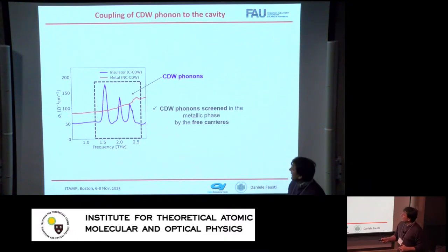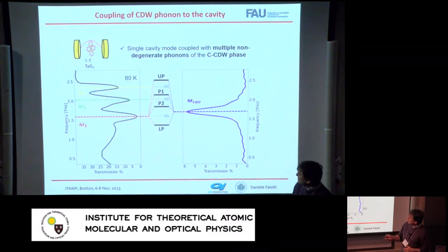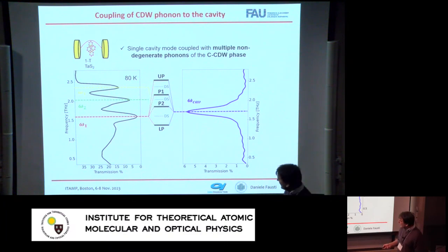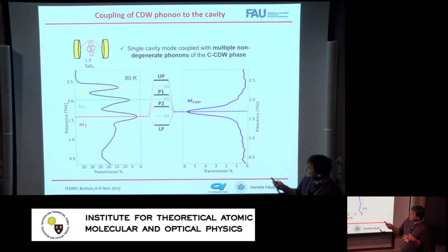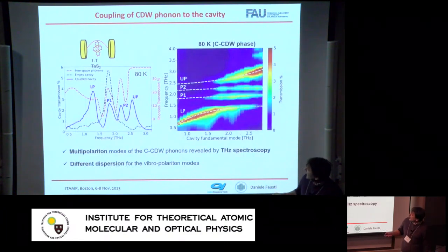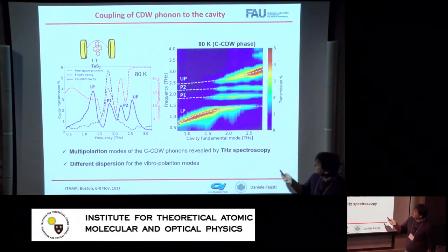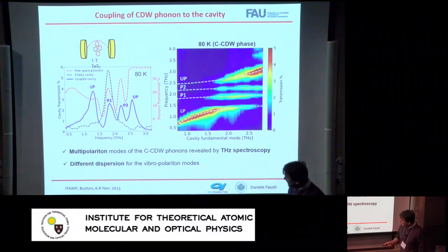Okay, and I can tune my cavity across this phonon mode, and what I expect is that if I take a sharp cavity resonance and I try to couple it with three phonon modes, I start with 4 states, and I should get out with 4 polaritonic bands. Nothing really peculiar happened. I just couple this object to these phonon modes, and I can study the coupling of the cavity to these phonon modes, and I can observe the polaritonic states dispersing and the two states in the middle which are not dispersive.